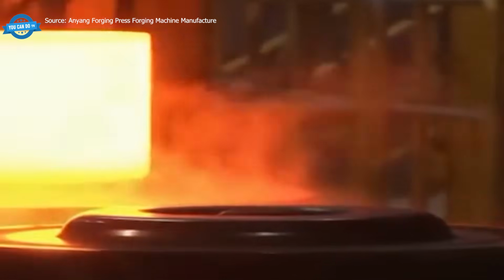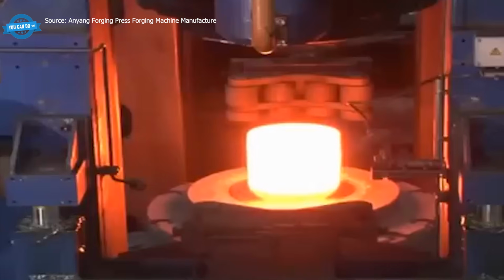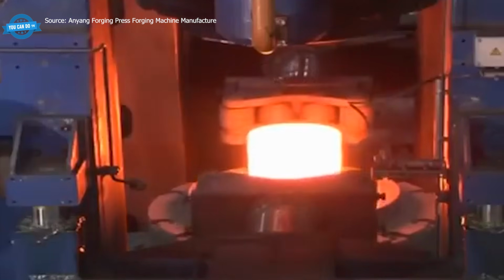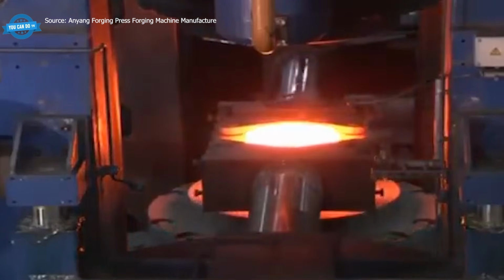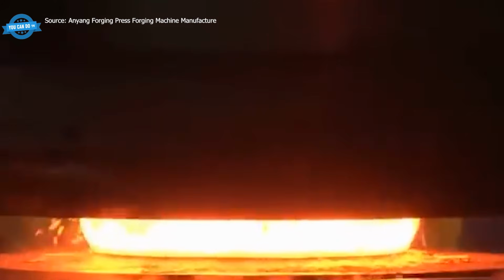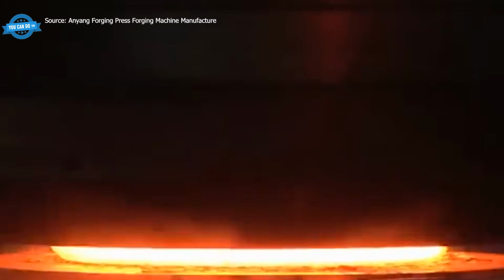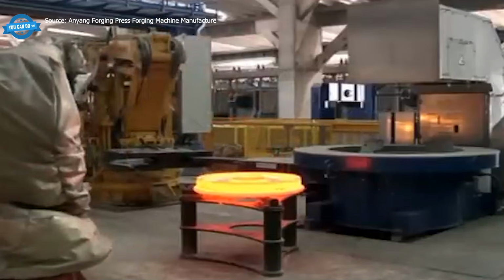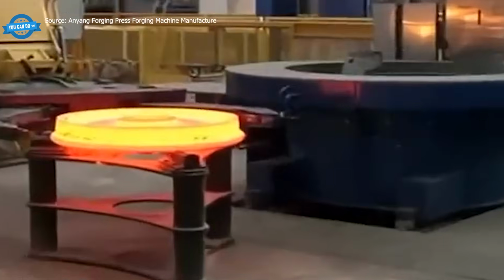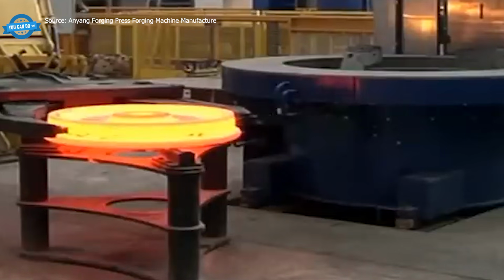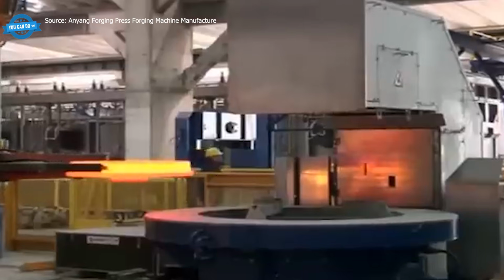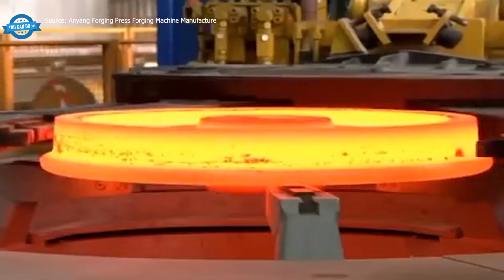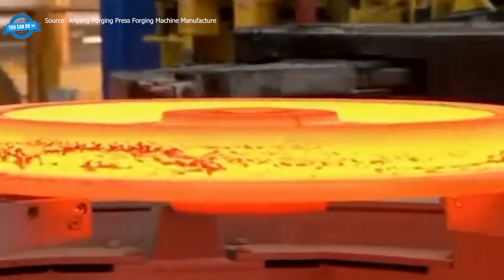Forged train wheels follow a different route. A hot blank enters a closed forging die and is shaped in a single blow, then rolls to a mill that finishes the rim profile to precise dimensions. Between cycles, the dies are sprayed with lubricant to keep hot steel from sticking and bringing production to a halt. Laser sensors check wheel diameter at every stage, because the tolerance for a wheel running at 300 kilometers per hour leaves almost no room for error.